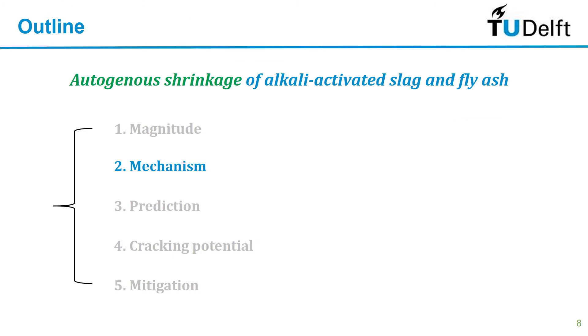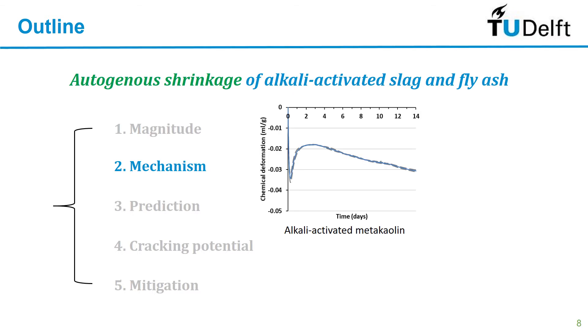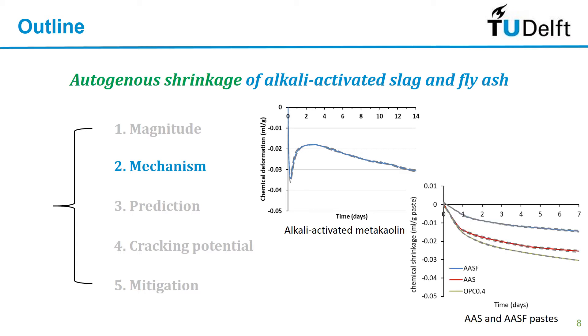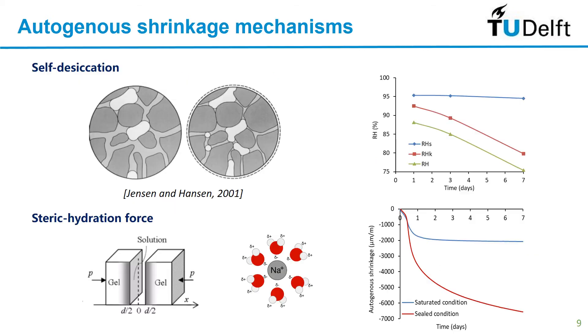When we talk about the mechanisms behind, we first need to think about chemical shrinkage, because chemical shrinkage is the root reason of self-desiccation. For Portland cement it normally shows chemical shrinkage, but for alkali-activated materials not necessarily — for example, for metakaolin-based geopolymers we found chemical expansion. However, for slag and slag-fly ash blending systems they normally show chemical shrinkage, which makes our research a bit easier. Chemical shrinkage means the reduction of the total absolute volume, which means the formation of internal voids and menisci that can induce capillary tension.